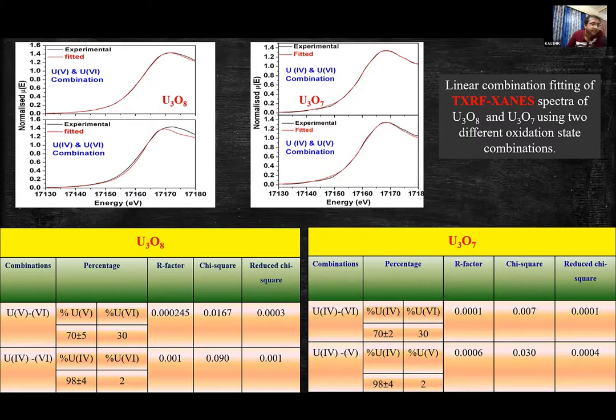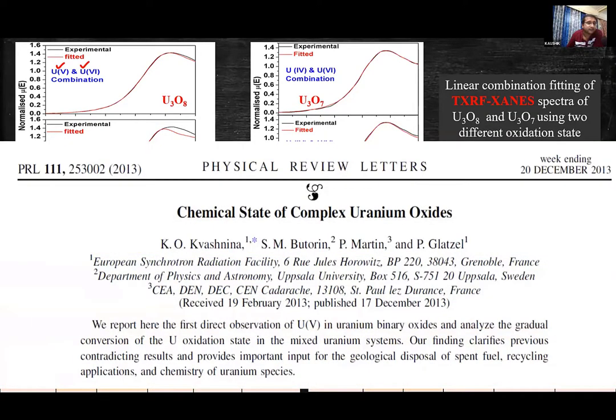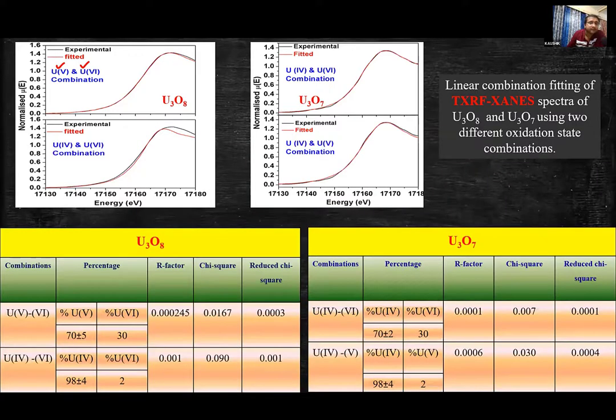So previously, many people thought that U3O8 was basically composed of uranium +4 and +6, but our study, as well as one study that has been reported in PRL, proves that in U3O8, uranium is basically present as uranium +5 and +6. So this is the work that has been carried out. And the same thing has been done for this type of mixed valent uranium oxide, that is U3O7. And it was seen that in case of U3O7, uranium is present as uranium +4 and +6.